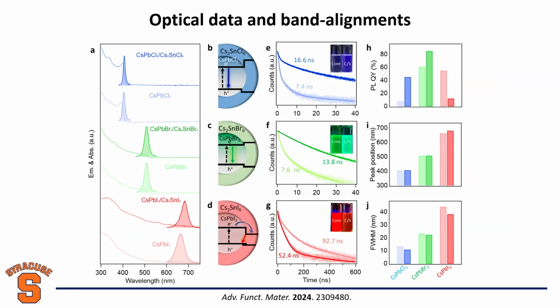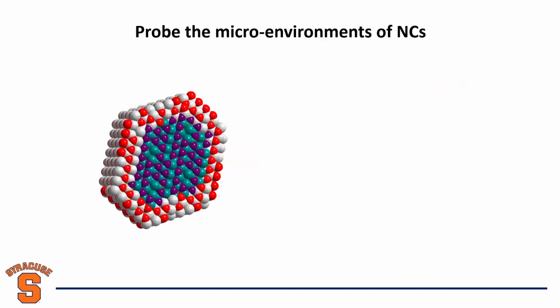But for iodide-based core-shell material, you can see you get type 2 core-shell. This is the band alignment. So basically, the shell is not wider, they have a staggered band alignment. The conduction band edge of the shell is lower than that of the core. So basically, electrons can migrate outside to the shell, and holes can stay here. So you can see I can physically separate electrons and holes at different locations of the core-shell nanocrystals. That can be very interesting or promising for photovoltaic or photocatalytic reactions, right? Okay. So this is the synthesis, stability and shape control.